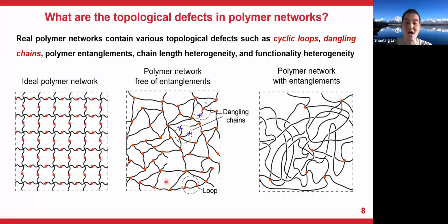And if all the chains are active, they still can be present in the form of defects in the form of cyclic loops, as we show here. And the number of the cross-linkers inside the loop determines the order of the cyclic loops. So what we schematically illustrate here is a secondary loop. And for highly concentrated or interpenetrating networks, the neighboring chains can feel interactions with each other, giving the defect in the form of molecular entanglements. Due to the limited time of today's talk, I will be mostly focused on cyclic loops and dangling chains. And we'll leave molecular entanglements and other defects for post-discussion if time allows.